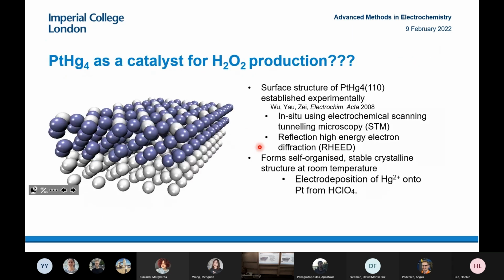The really nice thing about this was that we already found a detailed study where they elucidated the structure. If you take a platinum single crystal and electrodeposit mercury onto it, because mercury is very mobile, you can make a self-organized crystalline structure at room temperature, where you have isolated platinum sites surrounded by mercury. Usually when you're collaborating with theorists, they propose lots of different structures that are really difficult to make. But this one was really easy to make. To be honest, we found the structure before we did the DFT calculation, and we did the experiment as fast as the DFT calculation, which usually goes the other way around.